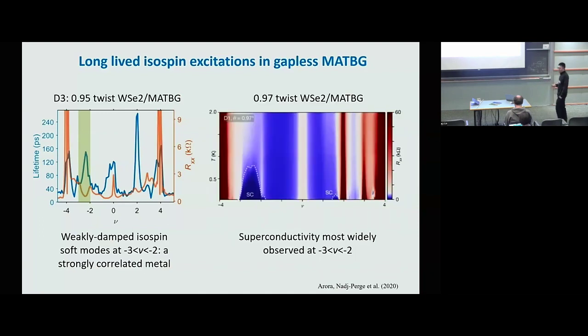Another interesting observation, which is quite common in all our reports, is that superconductivity seems to be most widely observed in this range. Since there are so many reports, I just pick one which has the closest device to us. So here we have a 0.95 degree MATBG with WSe2, and this device is a 0.97 degree MATBG with WSe2. So again, we can see that superconductivity is between -2 and -3.